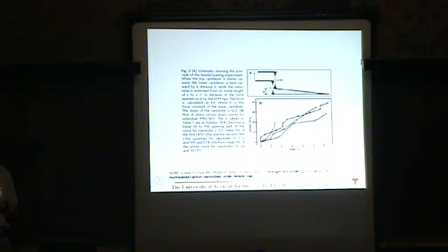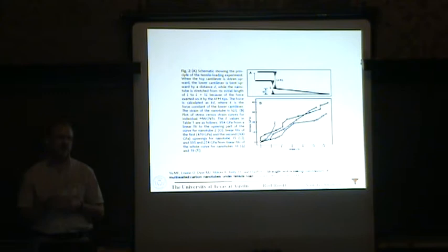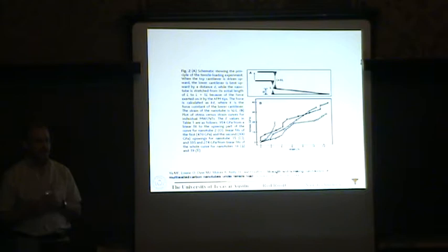Did you have any idea of how many walls were there? Not in these experiments. How many of those were really attached to what you did? How many of them kept attached during the experiment? We made a compelling case that we didn't actually have any breakage occur at the clamps, which was possible. For example, recently at Northwestern, we got samples of single wall carbon nanotubes that were selected for chirality and diameter by Rayleigh light scattering. Single wall, you can't do that. It's a different part of the story. In other words, when we did the same sort of clamping, we made measurements essentially the same way, and failure always occurred at the clamp. So those single wall carbon nanotubes were probably close to defect-free. Failure always occurred in the gauge length for all 19 multi-walled carbon nanotubes in this study.